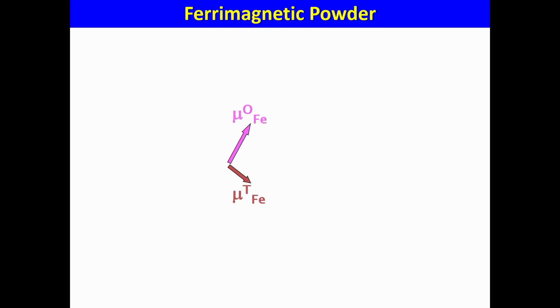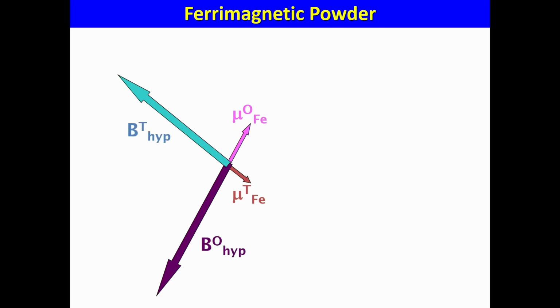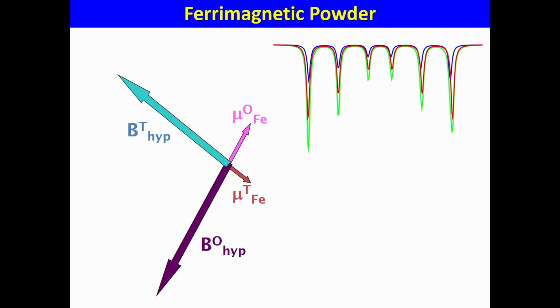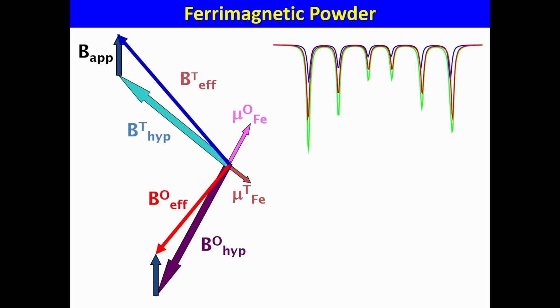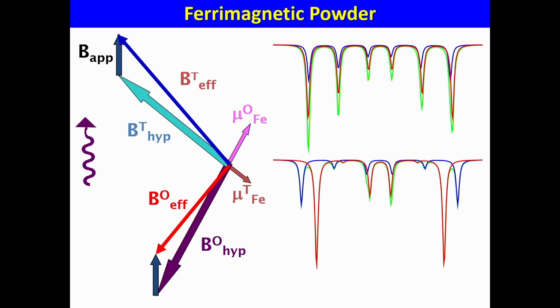And in the case of a ferrimagnetic powder, you have two types of magnetic moments, usually located in octa and tetra sites. So I will say before, the hyperfine field is opposite. So the hyperfine fields are there for tetra and octa. And if you do the spectrum, as I showed before, there is no resolution. Now you apply an external field. You can obtain the effective fields. And the spectrum you will obtain is like this. By such a way, you can estimate correctly the proportion of tetra and octa. In addition, you can also conclude what the mean angle is between the tetra and octahedral magnetic moments independently. Okay, so I will not discuss this because it's much more.